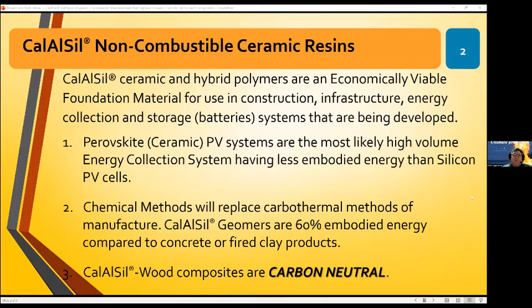So we really need to find something that is so ubiquitously obtainable in our world that you can make these concentrated solar panels from, and an aluminosilicate is the most likely candidate. So essentially, I've written a figure here of 60% of the embodied energy compared to concrete or fired clay. Some of my mixtures have been down as low as 45%. Typically, the non-combustible mixture averages at approximately 50 to 60% of the embodied energy. So it's a big step.